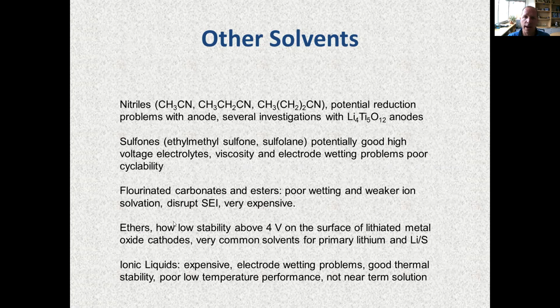But when you have a really high viscosity electrolyte, the electrolyte can't fill into the cell very well. And also it doesn't actually wet the electrode. So it doesn't go into and get absorbed into the electrode, similar to how water would absorb into a towel, where if you have a big puddle of water and you set the towel there, the water is wicked into the towel. Some of these solvents don't wet very well, and so they don't wick very well.